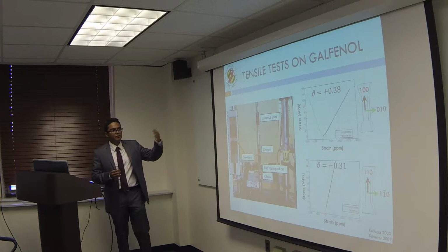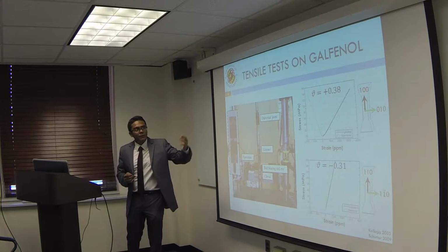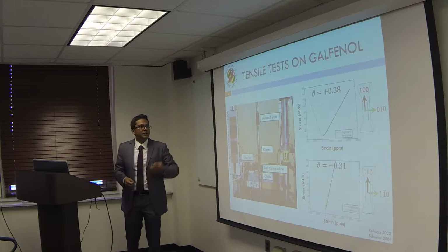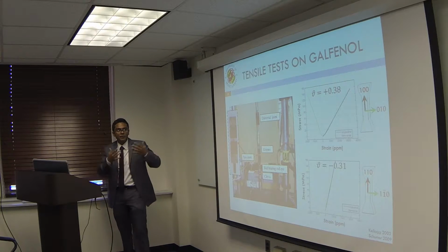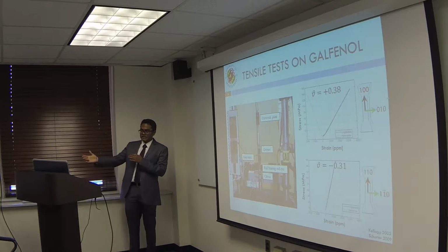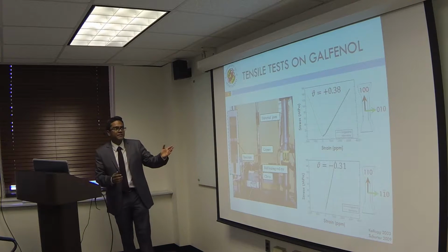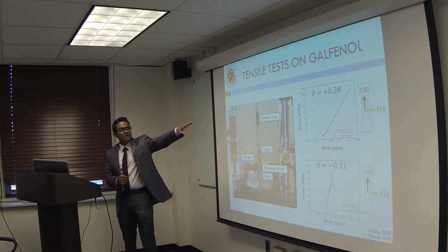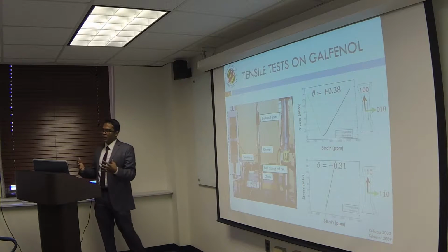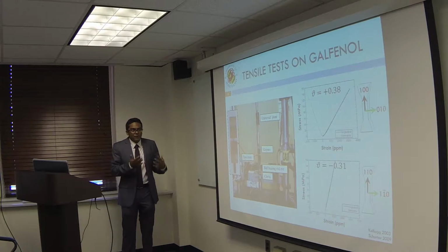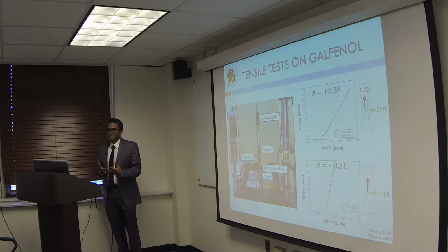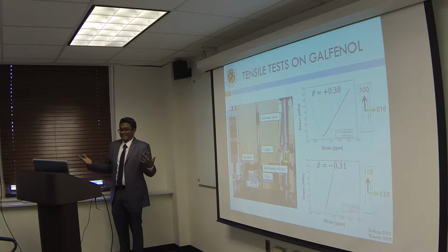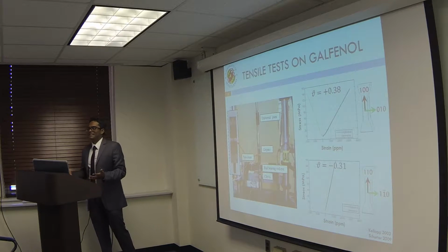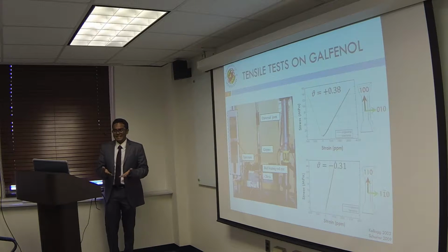And when he was looking at the different crystallographic directions, he found that when he was doing a tensile test along the 100 direction, he was getting a positive Poisson's ratio, which means there is an increase in the longitudinal strain and a decrease in the lateral strain, as shown on the chart above. But when he was testing the 110 direction, he was getting positive strains along both the longitudinal and the transverse directions. And his first thought was that his strain gauges were broken. But it turns out he had actually discovered auxeticity in Galfenol.